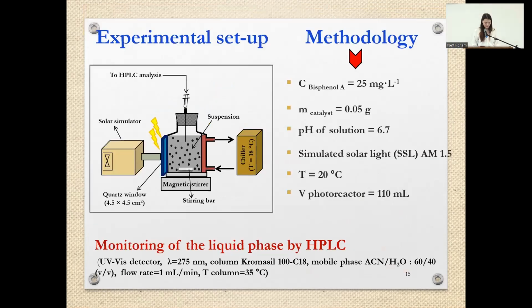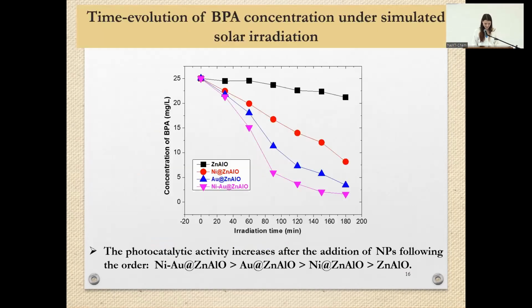The experimental setup can be represented in the picture. Here we have the reactor with a quartz window, a solar simulator, a magnetic stirrer with a stirring bar, and a chiller to maintain a constant temperature of 18 degrees. The liquid phase was monitored with HPLC. Here we can see the time evolution of BPA concentration under simulated solar irradiation. We observed that the bimetallic catalyst presents the best catalytic activity, followed by the gold catalyst, nickel, and the zinc aluminum oxide.